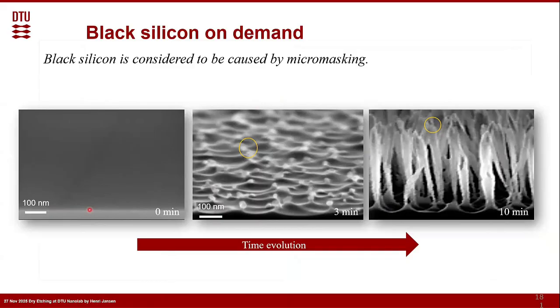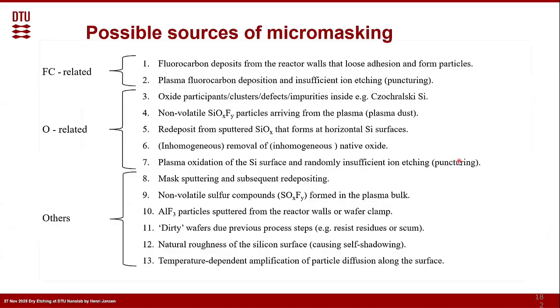And what we do is doing the bottom removal step, we didn't check it very carefully. And it seems that we did not remove maybe everything correctly. So during the bottom removal step, that's the step where we had the high ion flux, we are trying to remove the oxide or the fluorocarbon, but there's something left. And that will then create, let's say, little particles which are leftovers, and they are what we call then micrograss. And they will end up in every cycle, and when there's not enough undercut, they will really create pillars, and in the end, it will create black silicon.